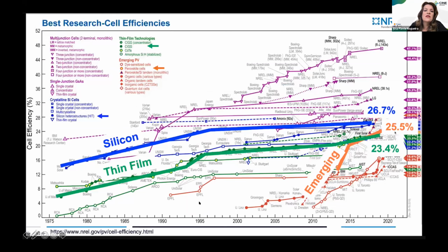If you could look here at these NREL charts, you have here the first and the second generation of photovoltaics. And you can see here down the bottom, the emerging photovoltaics, in the case perovskite solar cells. So you can see that the perovskite solar cells have recently achieved efficiency of 25.5%. This is above of silicon polycrystalline, and we are just 1% below the silicon, the monocrystal. So it's a huge increase in efficiency for this technology in very short period of time. So that's the reason that we really need to invest on this technology.